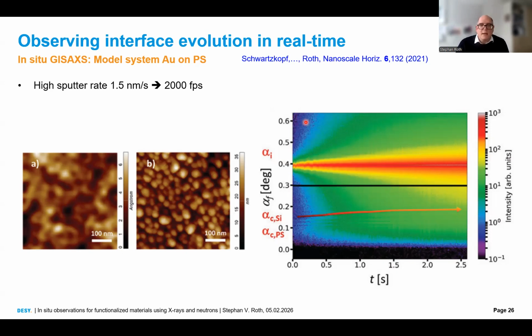We again sputter deposit gold on polystyrene thin film. This is again typically 100 nanometer. And in 1 second, you go from this image, excuse me, I need to drink something. Yeah, here to this image. So from a polystyrene layer to a cluster layer. And we take 2000 frames per second. This means when the whole experiment is 3 seconds, you get 6000 images in 3 to 10 seconds.